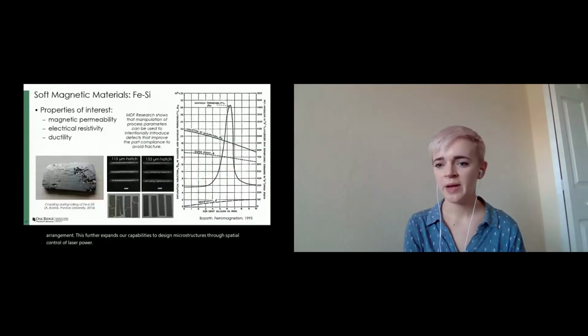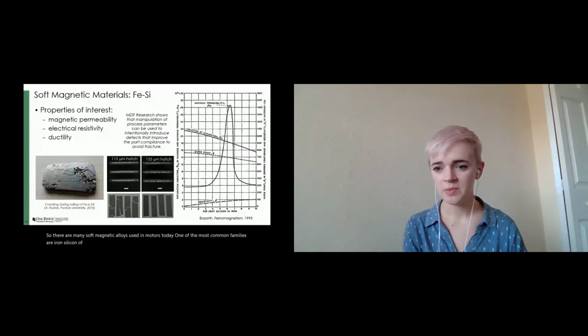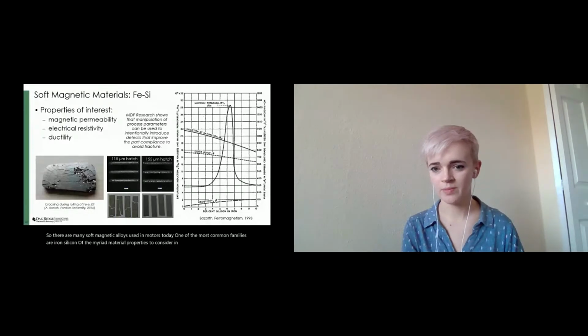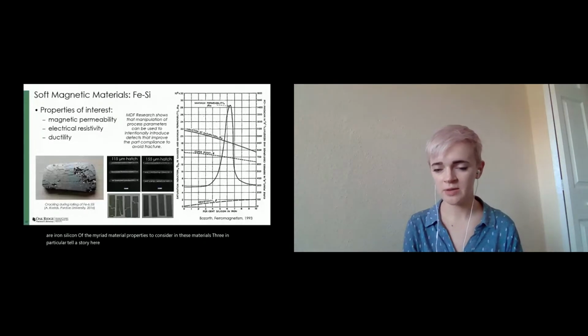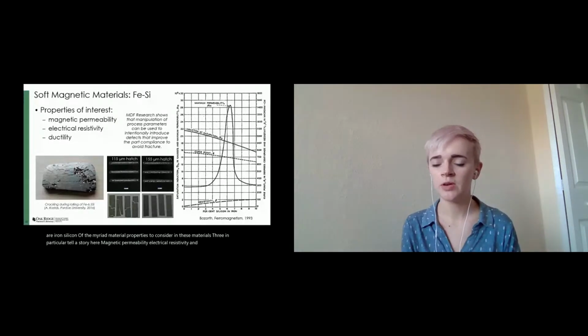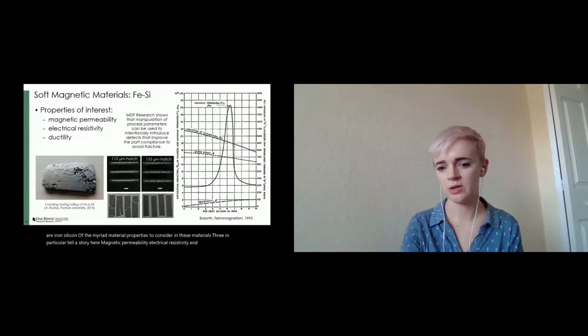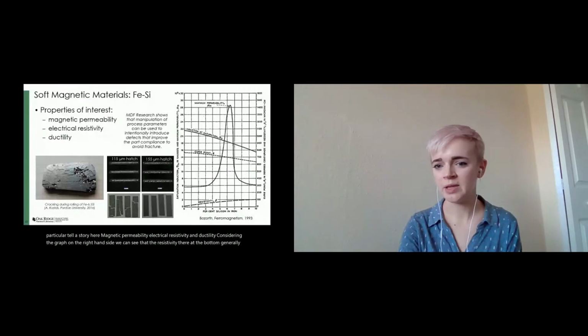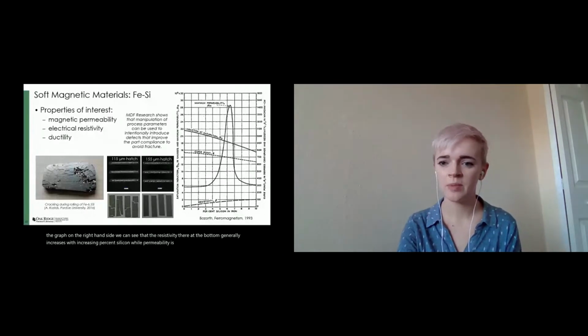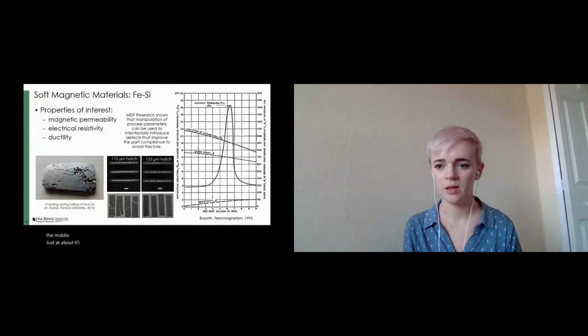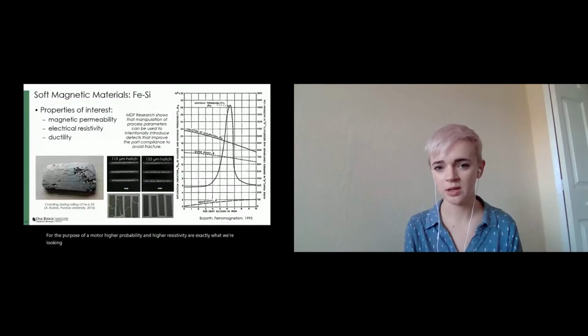So there are many soft magnetic alloys used in motors today. One of the most common families are iron silicon. Of the myriad material properties to consider in these materials, three in particular tell a story here: magnetic permeability, electrical resistivity, and ductility. Considering the graph on the right-hand side, we can see that the resistivity there at the bottom generally increases with increasing percent silicon, while permeability is this one with the big peak here in the middle, just at about 6.5% silicon. For the purpose of a motor, higher permeability and higher resistivity are exactly what we're looking for, so that 6.5% is looking like a great choice.